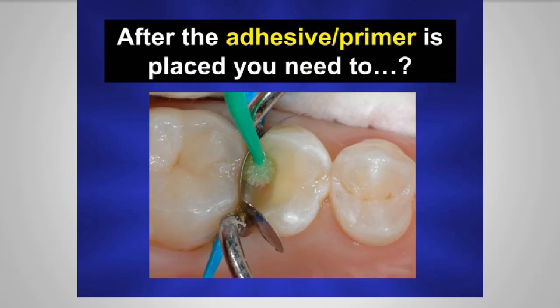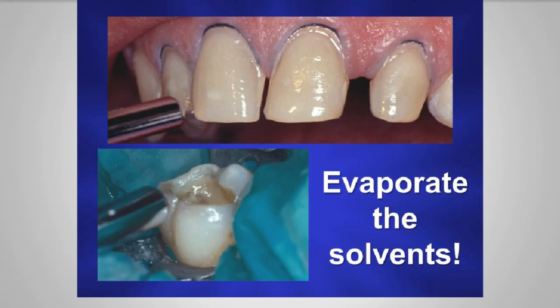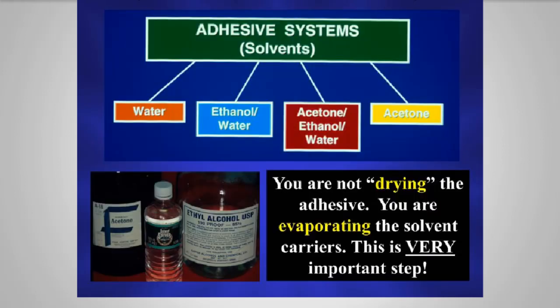You're not drying these adhesives. I mean, you're still leaving wet resin behind. What you're really doing is evaporating or getting rid of these solvent carriers. And this is a very, very important step, because if you don't get rid of all those solvent carriers, the material will still polymerize, but the degree of conversion will be much lower because you've left in a lot of these solvents. So very, very important. By the way, the best way to get rid of all these adhesive solvents is the use of warm air. And I use warm air routinely when I'm drying my adhesive preparations.